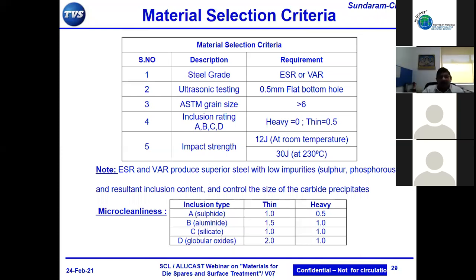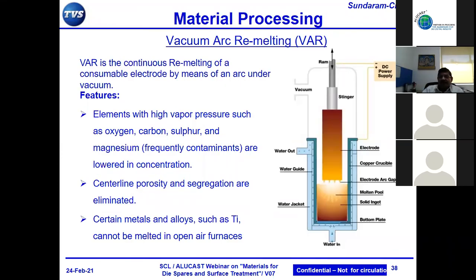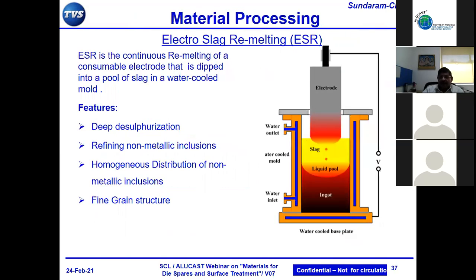Where we need to go into details in selecting the material, while you look at different H13 grades with ESR and things like that. Now, having gone into ESR, the first time I use the slag it is already contaminated with these intermetallics. The second time I use the same slag for the next electrode, the quality of the next ingot is not the same. So the first one could be a superior grade, the second one could be a premium grade.